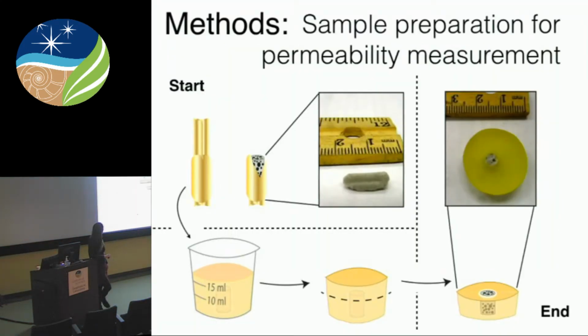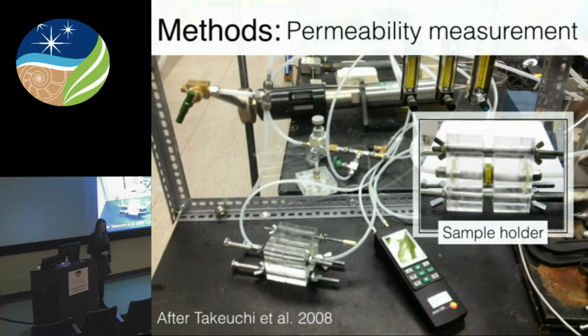Permeability measurement. So once the epoxy is allowed to cure overnight, the sample is then cut perpendicular to its longest axis and ground so that we expose a cross section. And this is kind of an aerial view of one of the experiments. We then measure permeability by sandwiching this little experiment into a sample holder. This entire setup we built at UAF to measure these small experimental samples. Conventional permeameters typically can't measure permeability on these small samples. So we can measure experimental samples on this permeameter, as well as natural bigger samples.